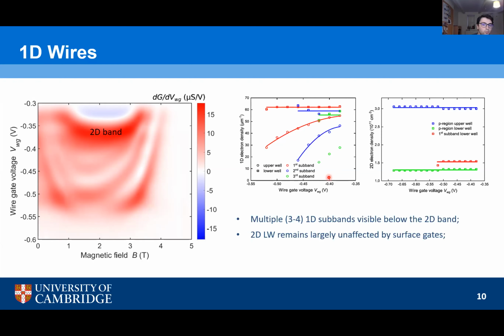The 2D lower well remains largely unaffected by the surface gates, and the 1D density varies from 15 to 55 electrons per micron. That corresponds to an rs factor, so the ratio of the Coulomb to the kinetic energy, from just below 1 to just above 2 for what I'm going to show today, though even right now we've been able to push this up to 3.